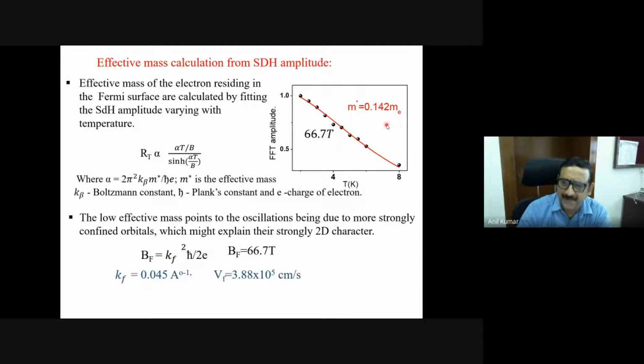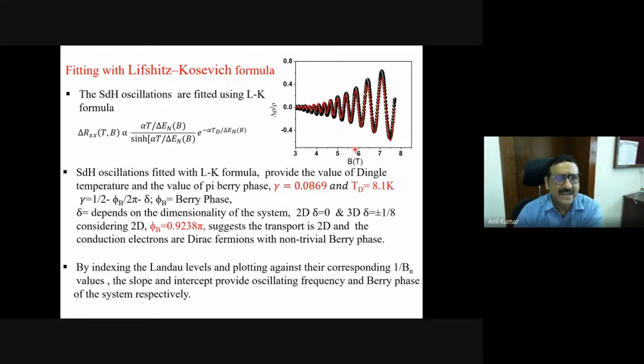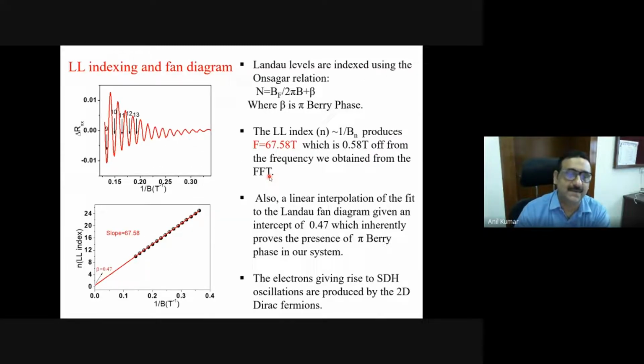The Dirac fermions appear to be like massless Dirac fermions because you have this linear dispersion, but we get around 0.12. So the effective mass has come down drastically, and we can extract a lot of parameters. You can also fit it with this Lifshitz-Kosevich formula, and again you can extract different parameters. And here again you extract the Berry phase of this material, which is pi Berry phase. So this is a very interesting and excellent system where you have a lot of information coming out.